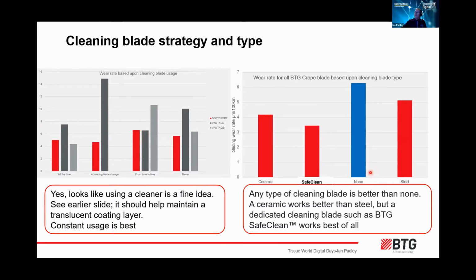Switching over to the other side here, what type of cleaning blade would you use? Well, any cleaning blade is better than none at all. A steel blade is still not as good as using a typical ceramic blade in that position. But a blade such as the BTG Safe Clean blade, which is specifically optimized to work in a clean position, by a small margin, admittedly, gives the best result of all in terms of keeping a good coating layer on the Yankee, and that's reflected in a good even wear on the creping blade.